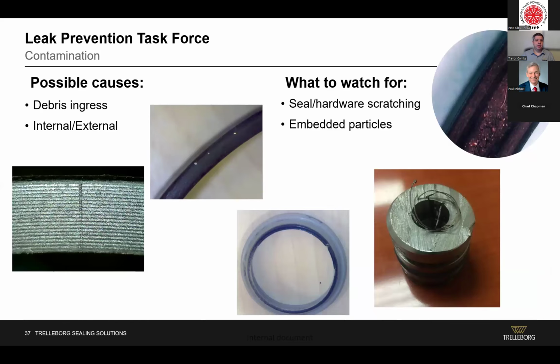And then for contamination, like I said before, it's a very common cause of failure and critical to address. You can have debris ingression caused by external or internal sources. You can see in the picture on the left a wear ring that got scratched by some hard particle, and that can cause damage to the hardware and the seals. The pictures on the top are of O-rings or other elastomers that have metal particles embedded. Once they get embedded, they can start scratching the surface as well, and that can cause leakage.